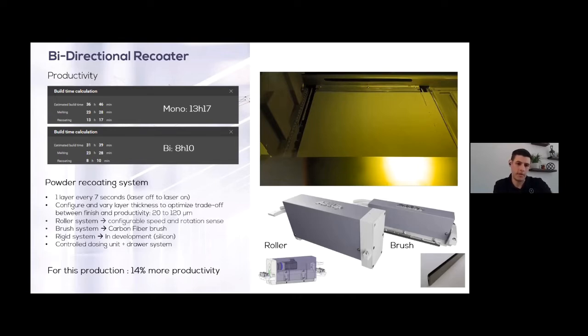So we just have an example here for a normal 36-hour build, or what would require 23 hours of laser on time. If you had a monodirectional recoater, you would spend 13 hours recoating. With a bidirectional system, that's reduced down to 8 hours. So in total, that's about a 14% total increase in productivity just by being able to recoat from both sides.